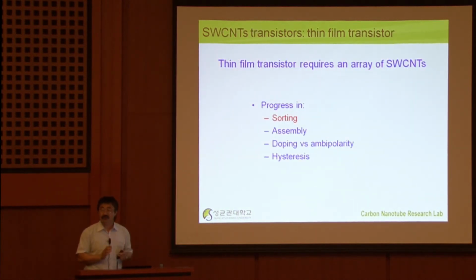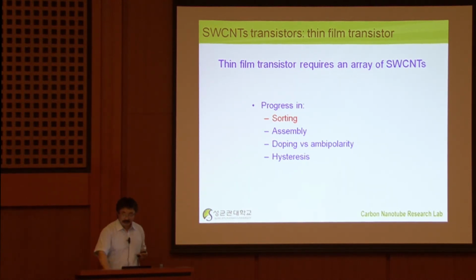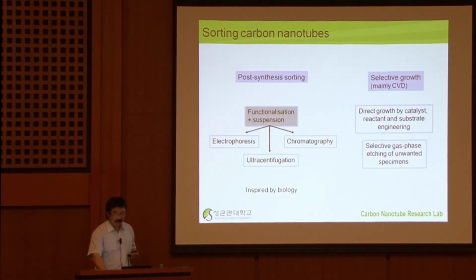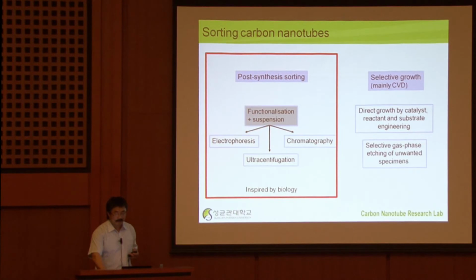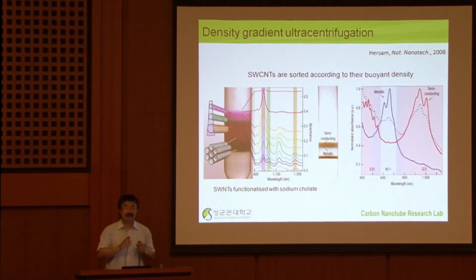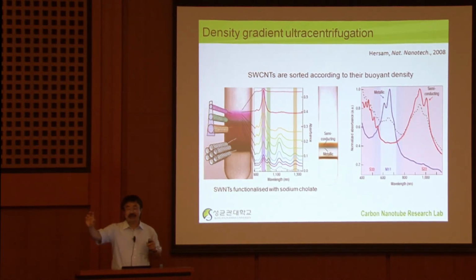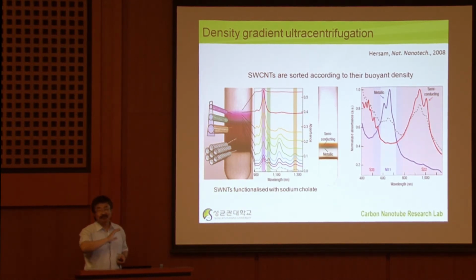So people try to use this random network CNT. But in order to make this random network CNT, we have also many other problems. One big problem is in CNT powder, we do have a mixture of metallic carbon nanotubes and semiconducting carbon nanotubes. Of course, for the active channel, we need semiconducting carbon nanotubes. But this is a mixture, so we have to select or separate the semiconducting nanotubes from the metallic ones.